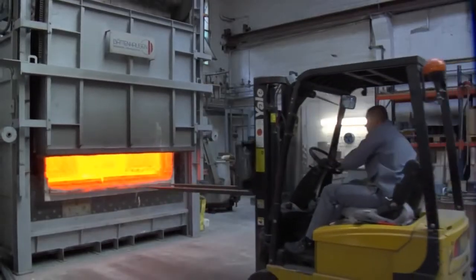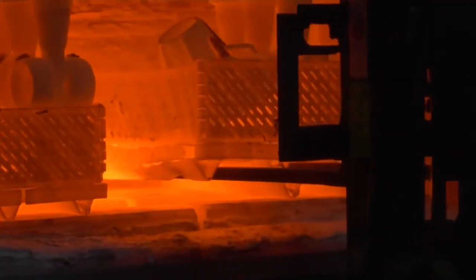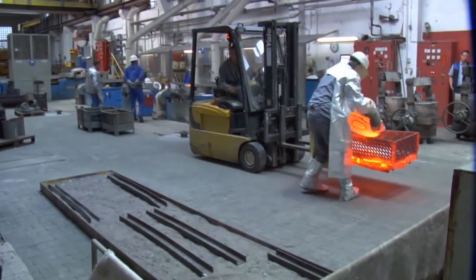The plastic models soften at 80 degrees C and shrink so that tears cannot form in the ceramic shell. Finally, the 3D printed model is burnt out from the casting die in the kiln. The plastic models burn out with virtually no residue.